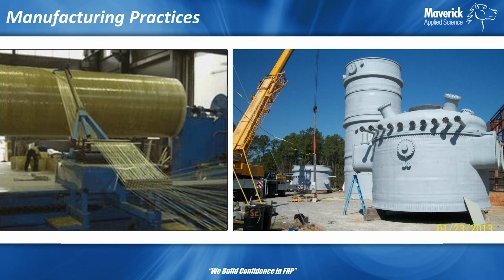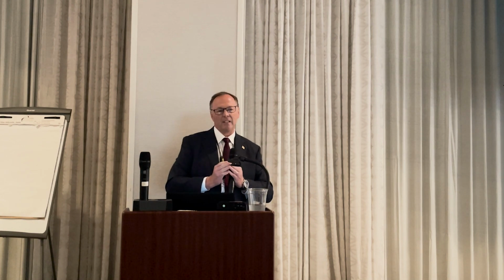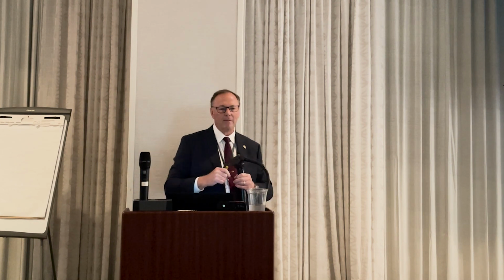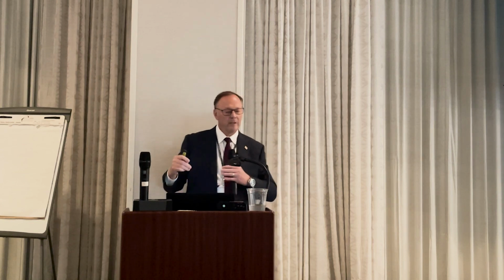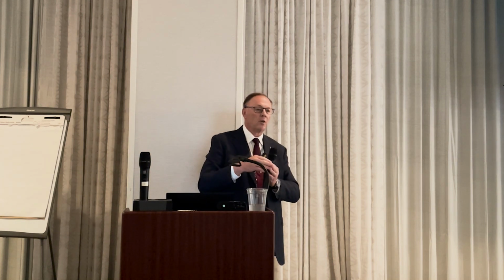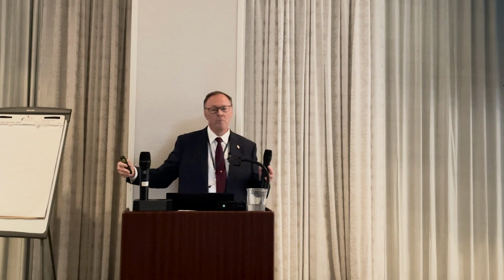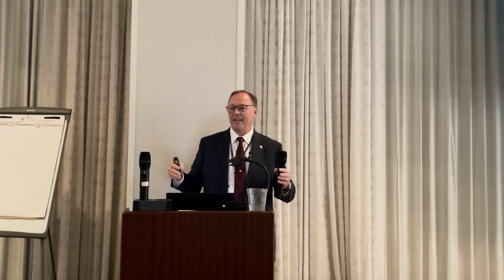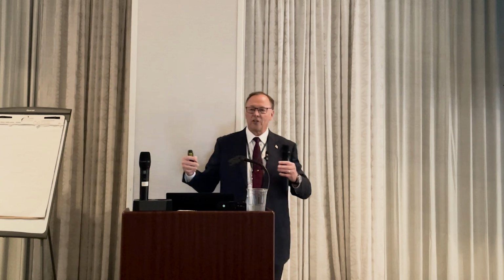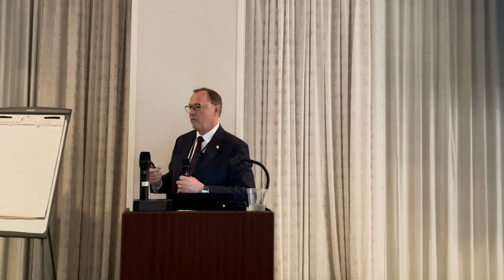So pretty cool stuff. Again, on some of the manufacturing, we've done a lot with piping. We've understood what makes it work well. We talked about the custom winding. As Jose said, that 55-degree wind gives us that perfect 2-to-1 pressure envelope for the pipe, so we get twice the hoop strength as the axial strength. But if we wanted spans, we could move that to 45 for tanks. A lot of times you'll see us going to 70, 75 degrees, because the hoop strength is more important, because it's just a static tank. There are no spans, and really it's just pressure containment we're worried about there. So for tanks, we'll see the winding go to something like 70, 75, 80 degrees in wind angle.